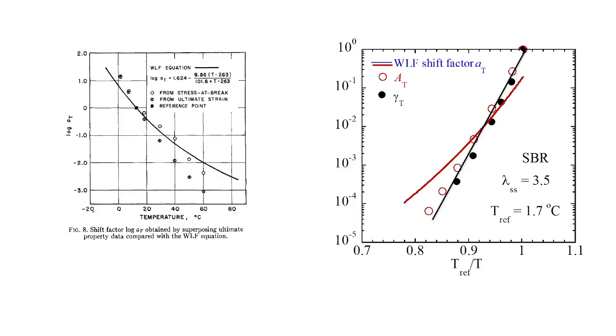He did it for different temperatures, so he can claim that there is a temperature dependence of this phenomenon. For example, at the lower temperature, it takes longer time because polymer relaxation is longer. So the WLF will give you that fit. So he fit them. This is the fit. And it looks like, oh, it fits quite well. The red is the WLF, and the symbols are the data. Except if you properly shift this data vertically, you find they are systematically deviating. Okay? So let me repeat. It's the same data. You just need to look at them, and then you realize something is wrong.